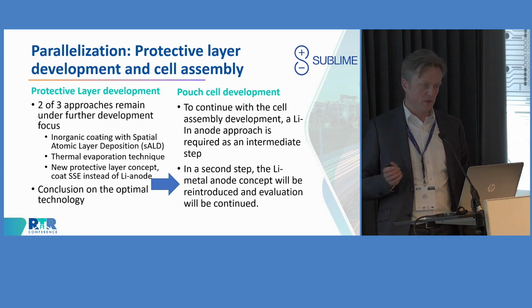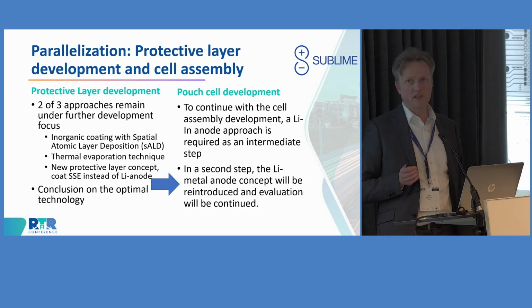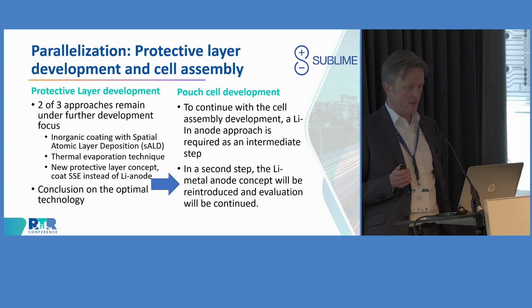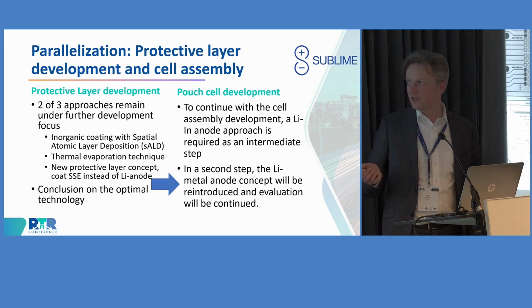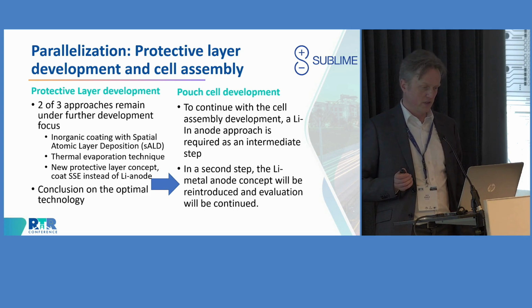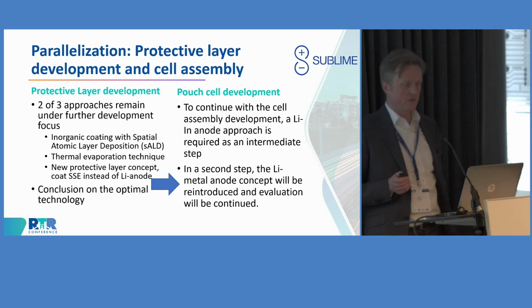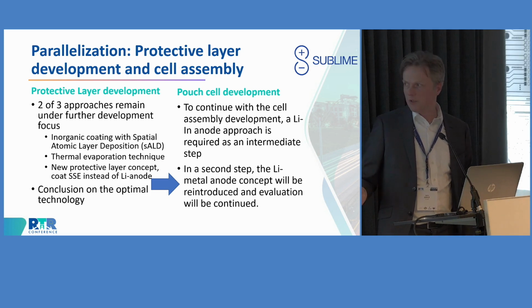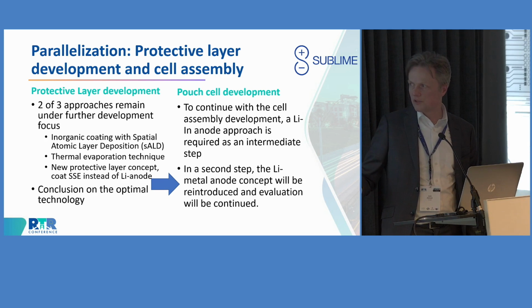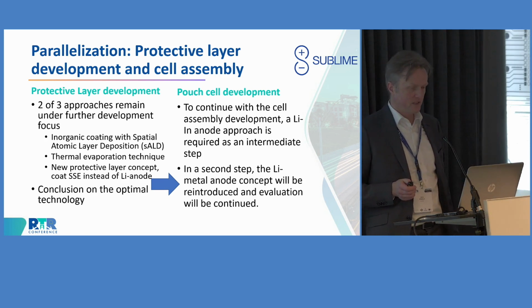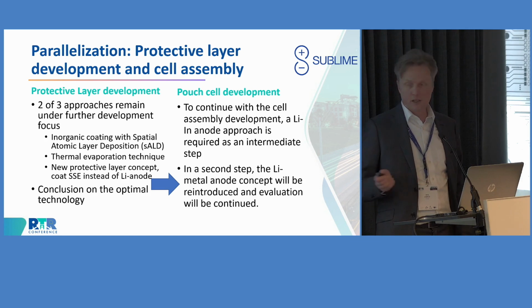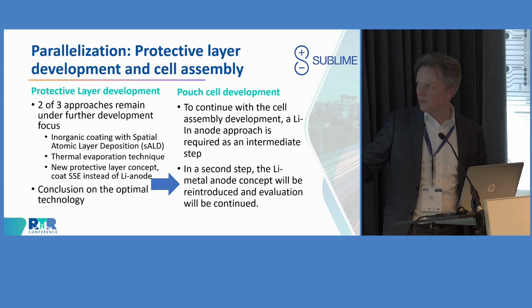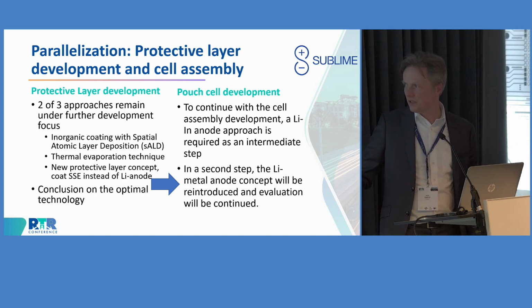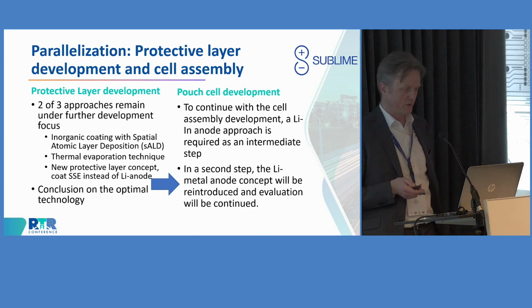We continue on the development of the protective layer for the anodes. So we had investigated 3 different approaches, and we will then still use 2 of those approaches under further development. You see here the sALD method, the so-called thermal evaporation technique, which we will use in order to further develop our protective layer for the anode. Maybe we will also look at using one of these 2 approaches, then at a different concept, how to protect against the dendrite formation between the anode and the solid-state electrolyte. And once this is done, then we merge again with the developments of a solid-state electrolyte and the cathode in the lithium metal anode at the end. So this is basically the way how we want to do this.